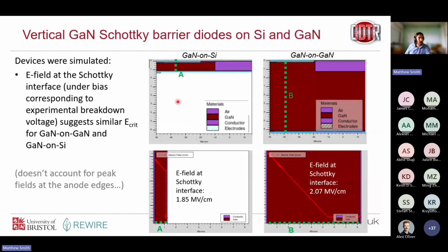Now, interestingly, if we look at the device simulation here, bearing in mind that for our GaN on GaN devices we have a much thicker epi layer, we do have a much higher breakdown voltage. But accounting for the thickness of the epi layer, what we find is that the electric field at the Schottky interface for GaN on GaN compared to GaN on silicon is not that different. It's something in the 10–20% range.